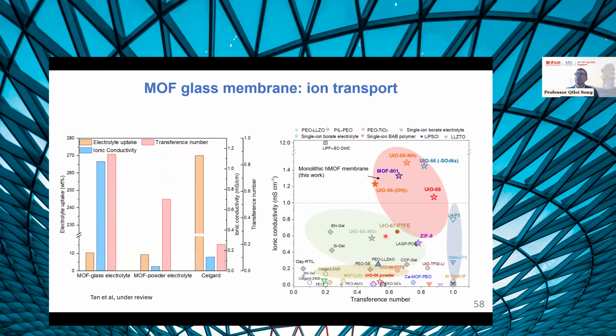Because our intention was to use this material for ion transport, we compared this MOF membrane with traditional materials, for example, Celgard. Because we densify these MOF materials, they absorb a relatively low amount of electrolyte, but they give really good conductivity and also a very high transference number. When you compare the ion conductivity with traditional materials, this MOF material gives much higher conductivity, and also a higher lithium ion transference number.